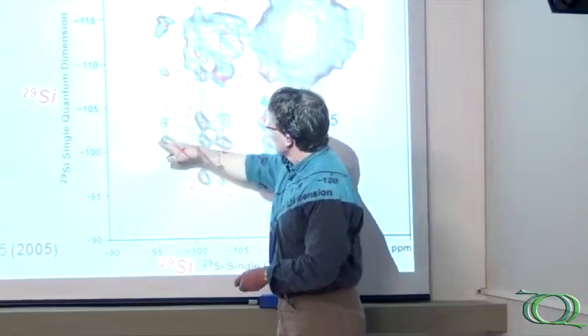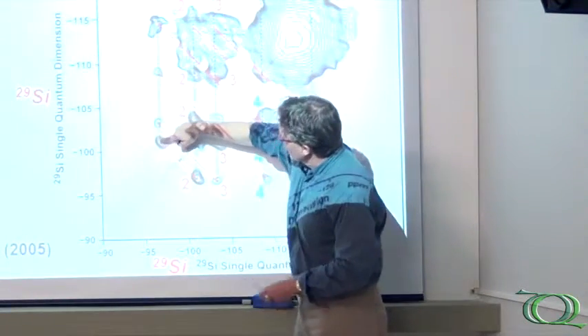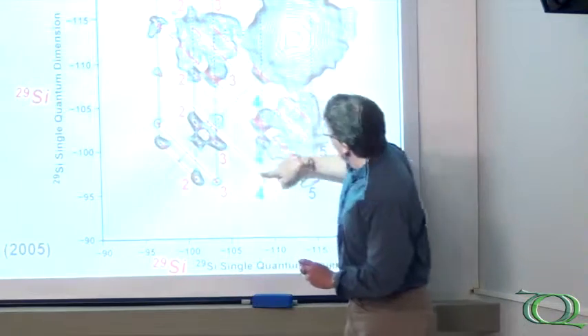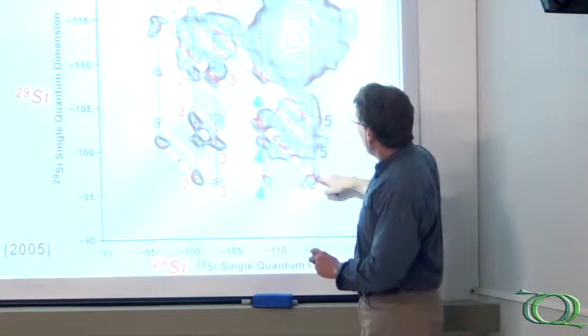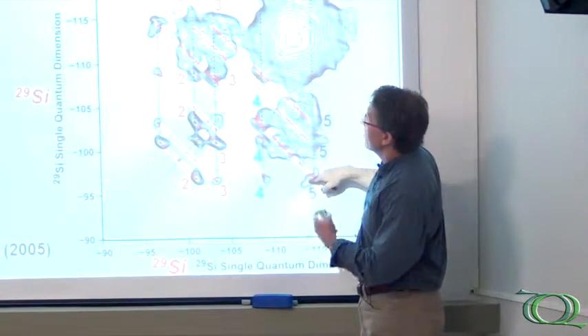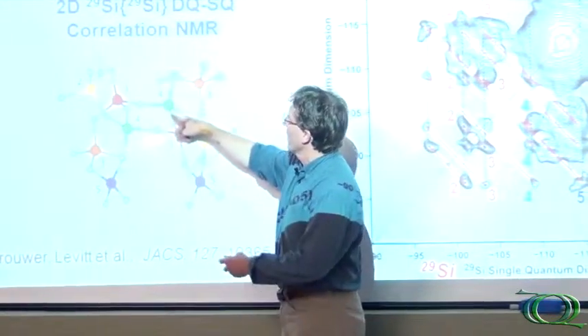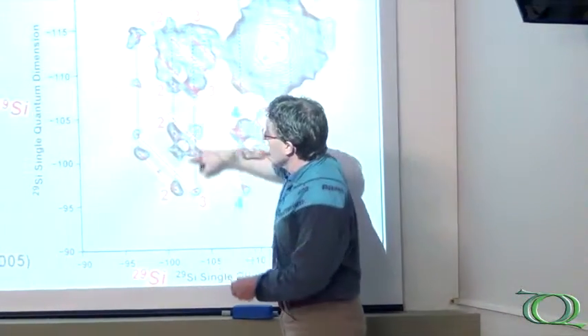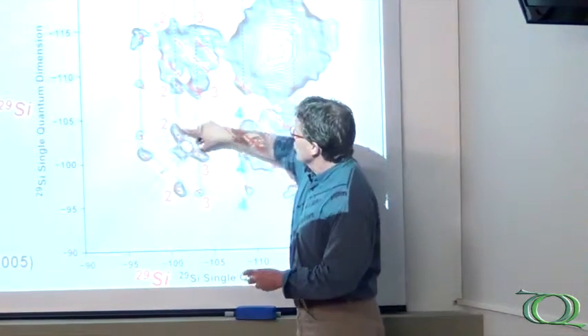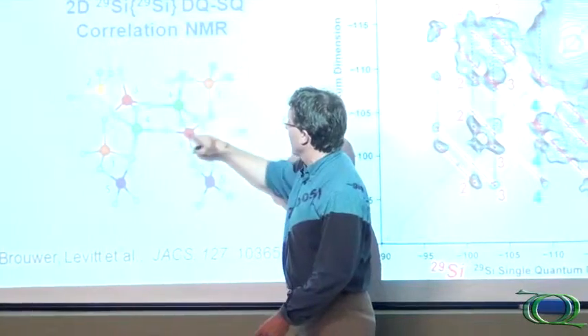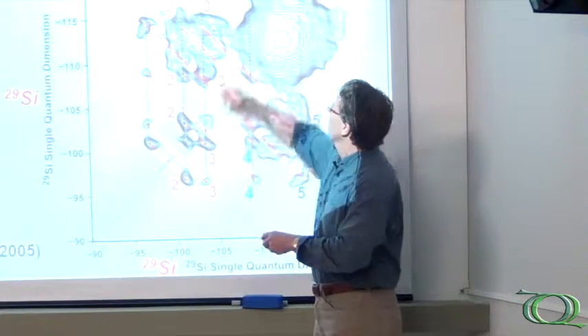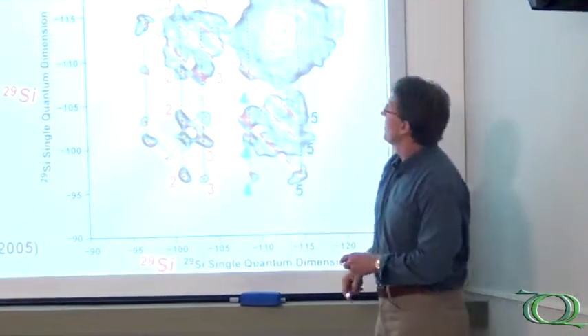But I'm going to call your attention to this, that you have now the opportunity to see from the silicon correlation that site one here is correlated with site two, with site three, with site four, and with site five. So all of these different correlations are consistent with the framework structure that I've outlined in this molecular building unit. Similarly, and so on, you can do it in reverse. You can then use all of these things to establish that the interconnectivity of these allows you to establish exactly which of these sites are interacting and strongly and in proximity to each other. And so this allows one to identify the structure and how these sites are interacting with each other to form the framework that we then continue to transform.